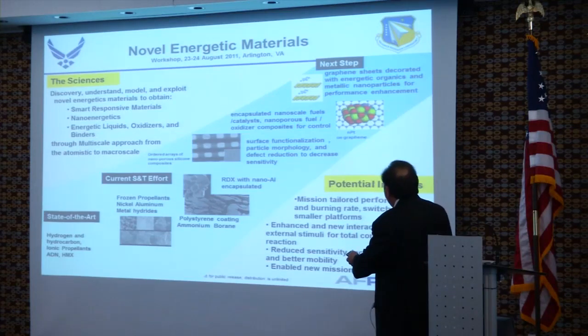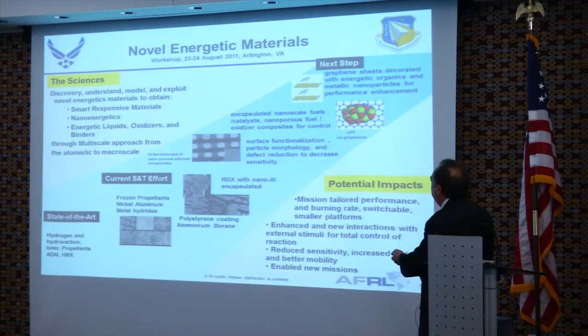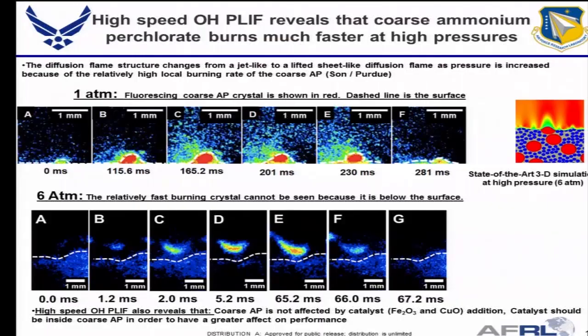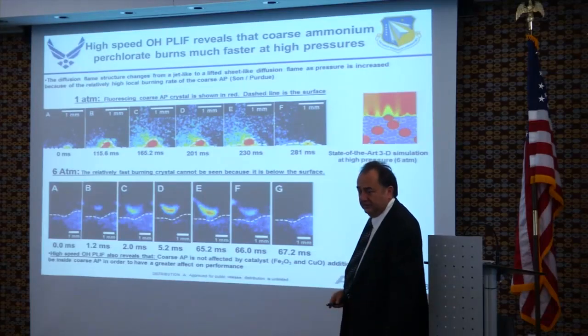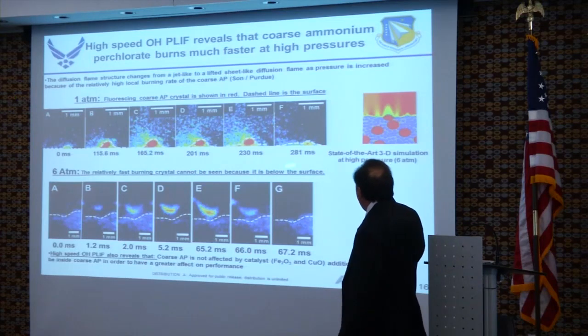8 minutes, okay. Now, let me show you some examples of what happened over here. One of them is pretty much showing how new tools can change things. Ammonium perchlorate has been studied for many decades, and it's been known that it has a slower burning rate. So when it is burning in a composite propellant, it will stick out, and it will burn in something like an inverted cone-shaped diffusion flame, because the ammonium perchlorate is oxidizer rich, and around it is fuel rich. And that's what has been used in the